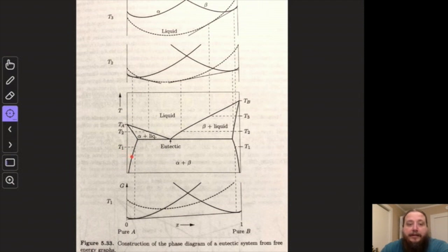Now, eventually, the time to reach equilibrium in a solid and mix the purity of these crystals out can get very, very long, and so in a practical substance, there is some effective freeze-out temperature below which the purity of the crystals doesn't actually change at finite time, even over geological timescales, if we're talking about the formation of these substances in various crystal forms.